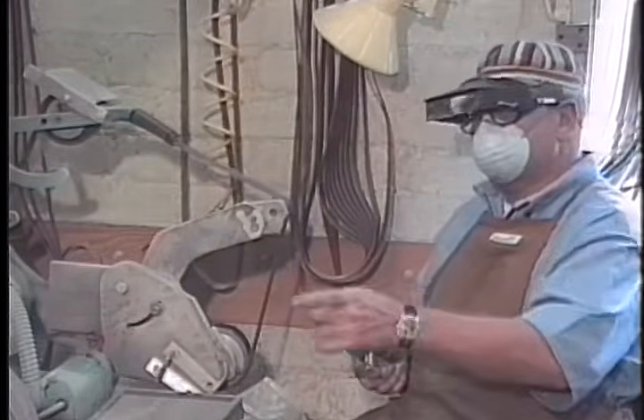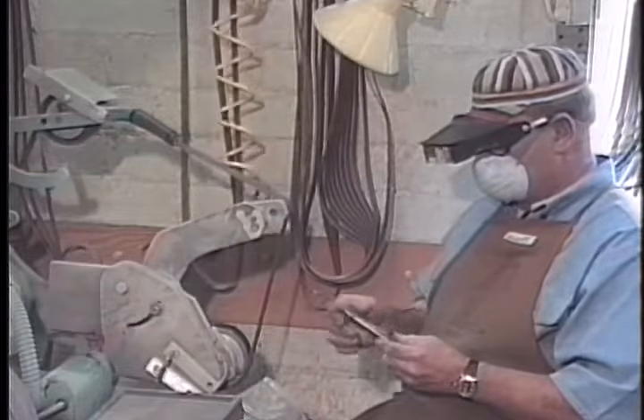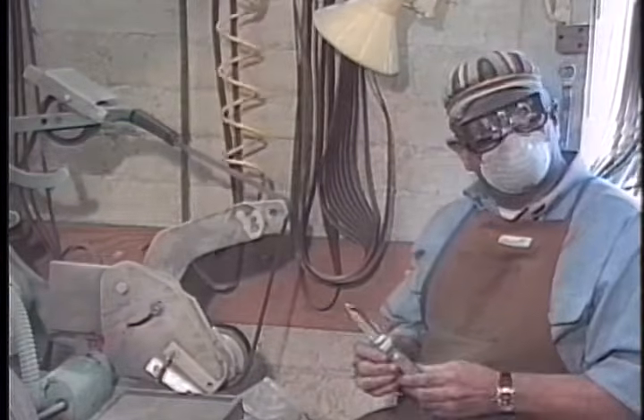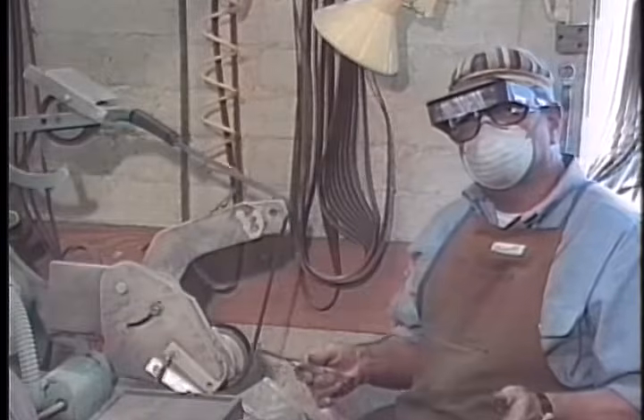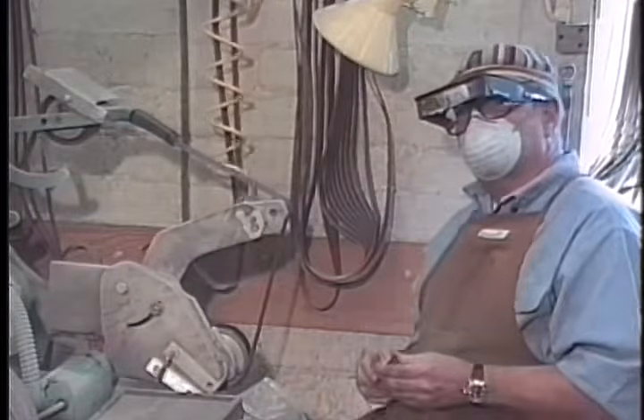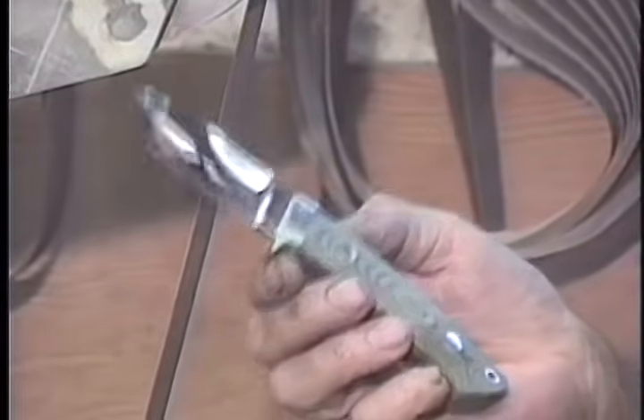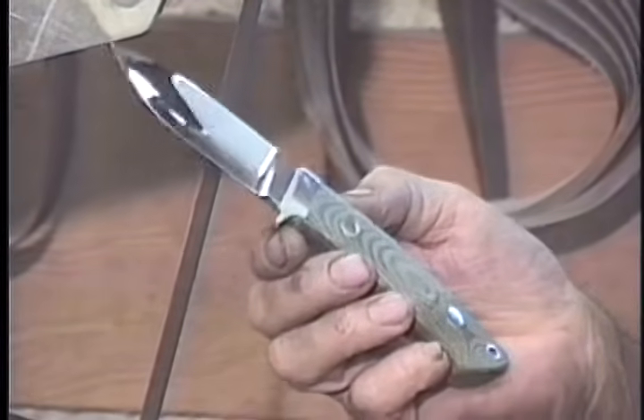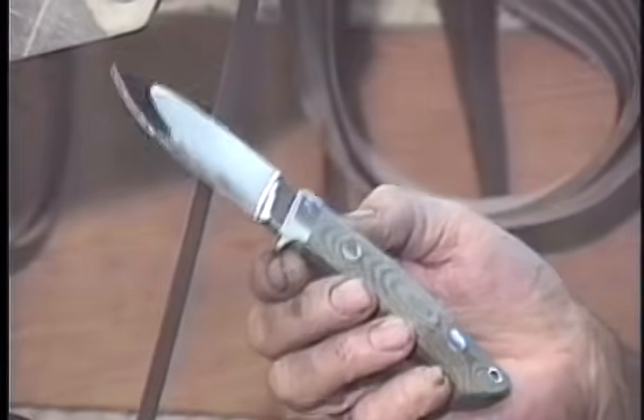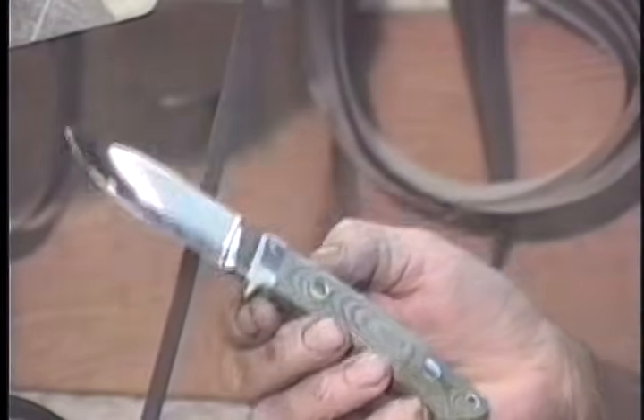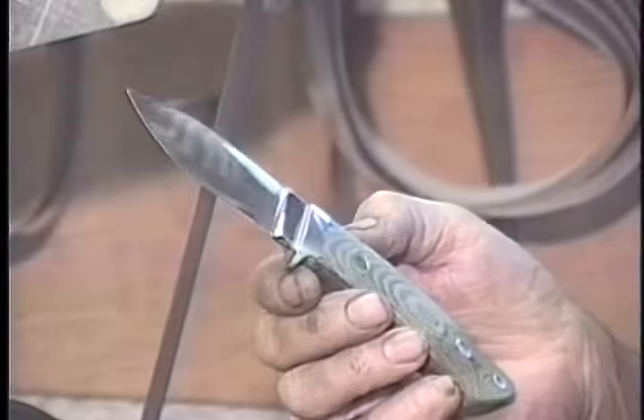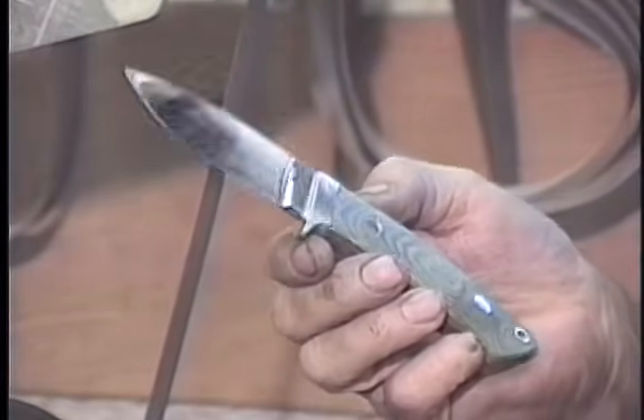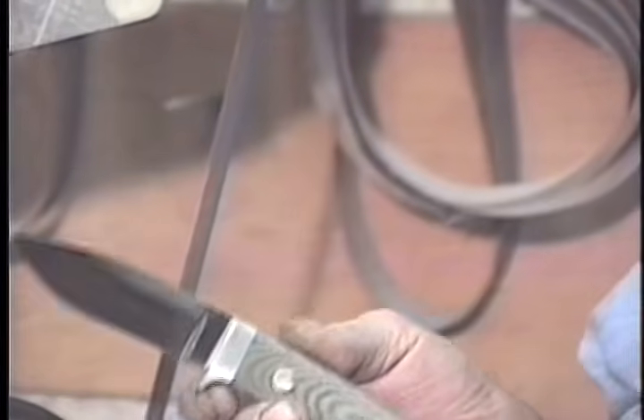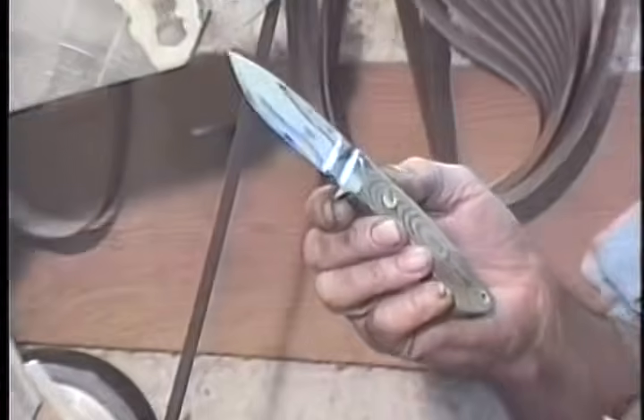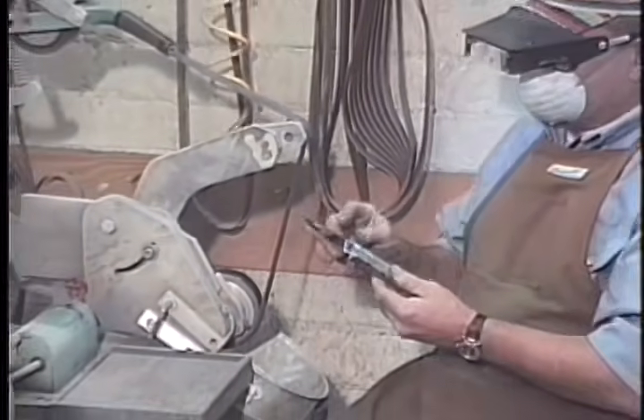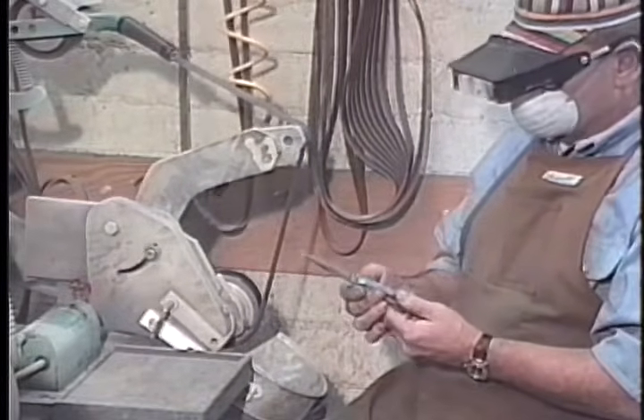Now, we roughed it in over there, we pretty much finished the shaping here. Now it's a matter of polishing out and getting it ready for the trademark and the leatherwork in the sheath. This steel must be mirror polished to give its best corrosion resistance. All stainless steels need a very, very finely polished surface to be the most corrosion resistant, or as some people would say, rust proof. That's not really true. But when they're highly polished, they're very corrosion resistant, whereas if they were less scratchy and everything, corrosion could get a bite. That's one of the reasons we put a mirror polish on these Loveless knife blades.